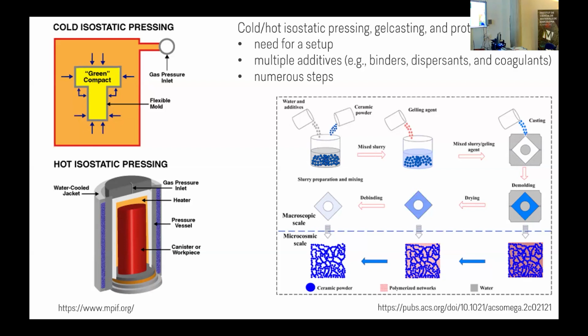And at the same time, sometimes they mix ceramic with a polymer so that they exploit the rheological properties of the polymer rather than the ceramic itself. So these are all composite materials. I'm against calling these things just ceramics, right? Because what you are relying on is the properties of the polymer, not the properties of the ceramic. And most of the time you have to use copious amounts of different types of chemicals, binders, dispersants, and these kinds of things. And then, of course, with the organic matrix methods, you have to remove it afterwards, right? In sintering, we are trying to densify the structure by getting particles as close to each other as possible. When you have lots of organic matrix around, you have to do a special burnout step to get rid of that matrix. So this is what is available.